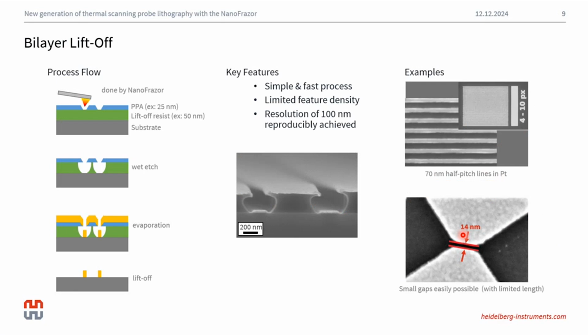Another pattern transfer technique that we use quite commonly is the bilayer liftoff, which I'm sure you're all familiar with. In this case, we have 2 layers of resist, the PPA on top as usual, and at the bottom a liftoff resist, which can be PMMA, PMMA-MA, PMGI, or any other liftoff resist that you're familiar with from fabrication. The way this works is again starting with a patterning step into the PPA itself. And this time, to transfer the features, we don't use a dry etching step, but rather a wet etching step.